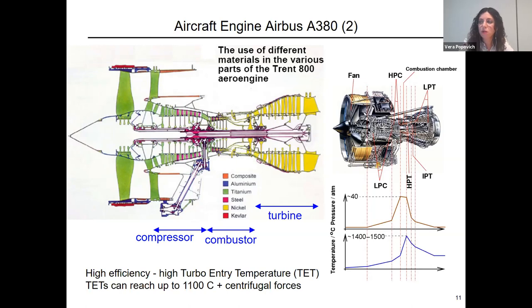In turbines, when we are talking about high efficiency, we're talking about turbine entry temperature, and the turbine entry temperature can reach up to 1100 degrees C. And that's, as I already mentioned, next to high forces, for example centrifugal forces. So it's no wonder that for turbine and combustor areas, in the past 20 or 30 years, a new type of nickel-based superalloys has been used in order to tackle high temperature strains and provide fatigue resistance for these specific areas.